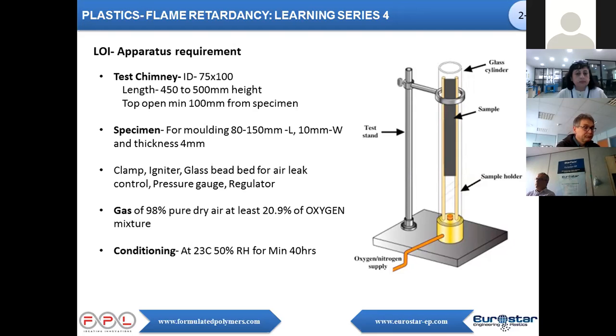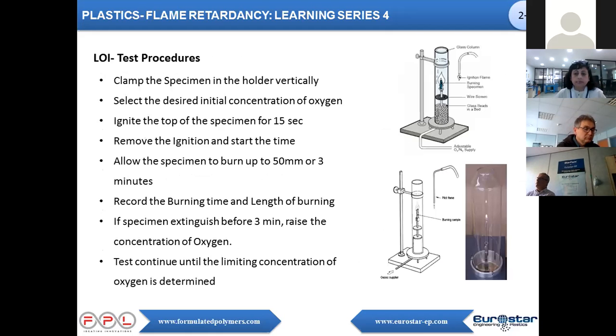Here pure air is used as gas. A 98% pure dry air with 20.9% oxygen nitrogen mixture flows inside the chimney as a gas. All ASTM IEC standards require specimen conditioning before the test. Test specimens are conditioned for 40 hours in desiccators at 23°C, 50% RH. Glass beads are placed under the specimen holders to avoid air leaks. Now we see the LOI values of materials.